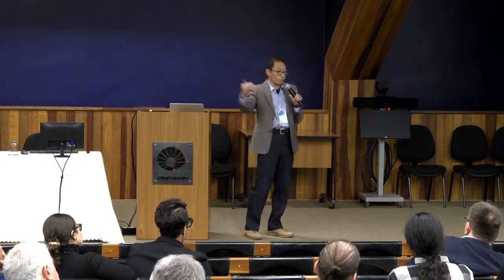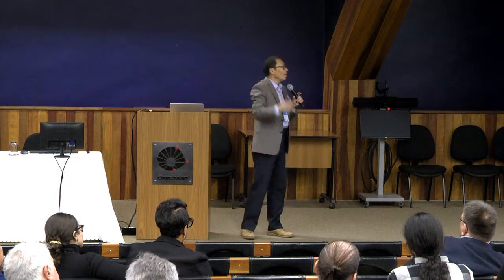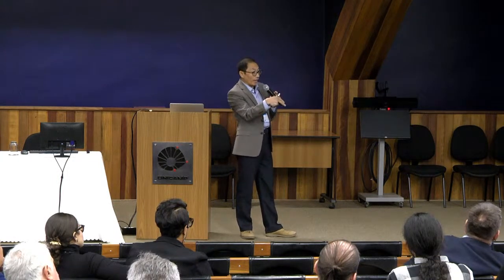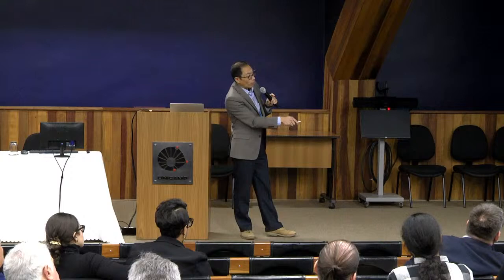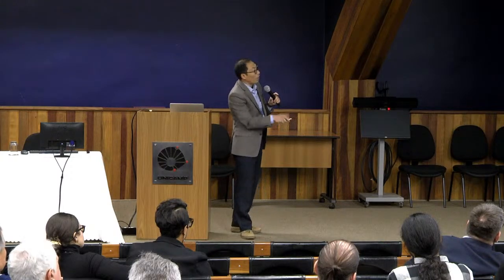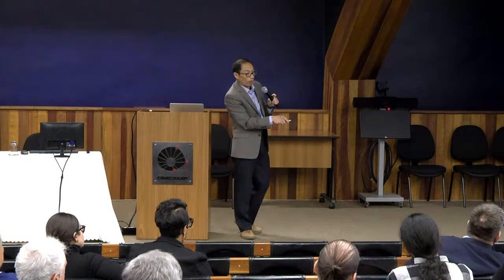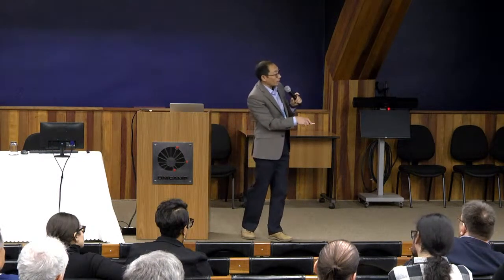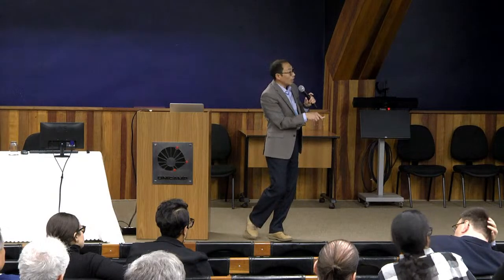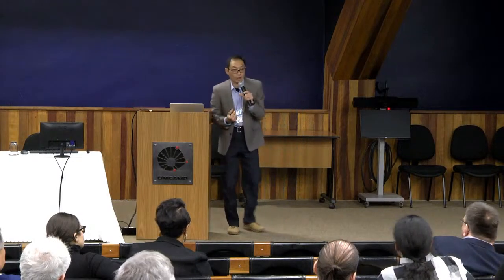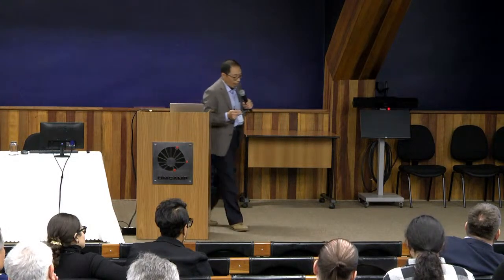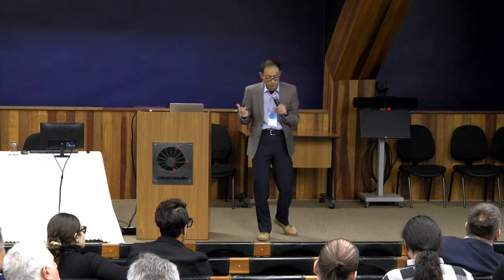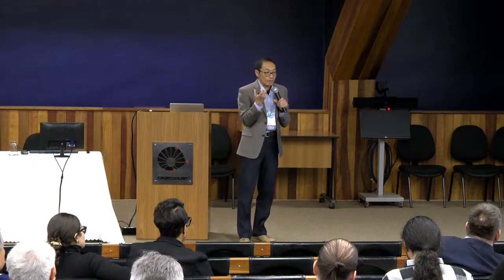And then we watched how the feature emerges in a perfect layered compound of lithium nickel oxide. They cycle beautifully up to 4.8 volts. But this one, they decay, and this is with a little aluminum doping. And then you can see how this feature emerges. So when you have this antisite or you just dope it directly, you will see this kind of oxidized oxygen feature showing up. So when we have a feature like this, it is very likely O-O bonding formation, peroxide or oxygen gas molecule.